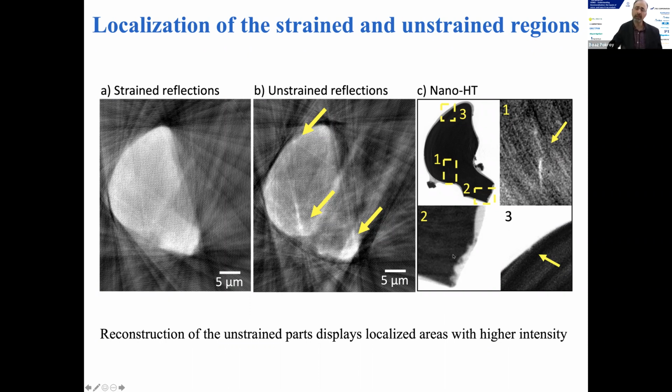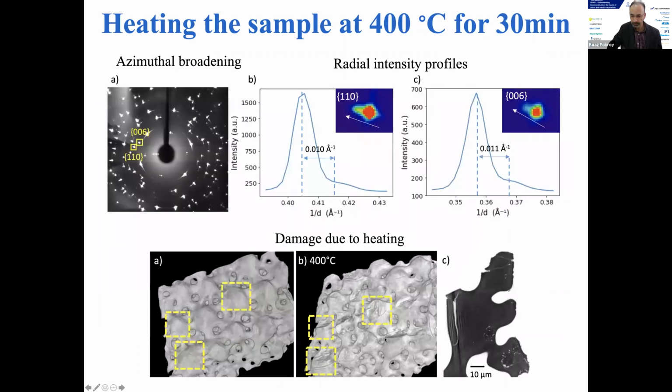So this is actually a very interesting thing that we have seen here that we haven't understood before, and we're still trying to fully understand it, is that actually when we powder these lenses, we actually relax part of the high compressive stresses that we see here in the whole, in the unbroken dorsal arm plate. And when a crack propagates, for example, it also seems to relax these high compressive stresses.